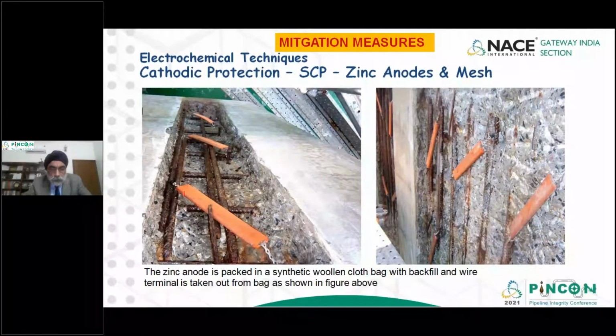Around the zinc anode, there is a synthetic woolen cloth bag with a backfill, the way we provide bentonite gypsum in our zinc or magnesium anodes which are embedded in soil. In the same way we are putting in a backfill which would retain the moisture and allow the zinc anodes to deliver current to the rebars. So here the concrete has been removed, the anodes have been installed, and the area will be repaired by putting in cement. Now these anodes will prevent further deterioration of the rebars.